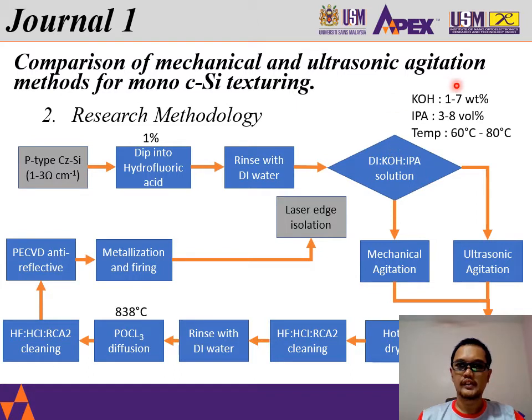In this journal, they evaluate KOH concentrations of 1 to 7, IPA at 3 to 8 volume percentage, and temperatures between 60 and 80 degrees C. The study is split into two techniques: the first is mechanical agitation, and the second is ultrasonic agitation.